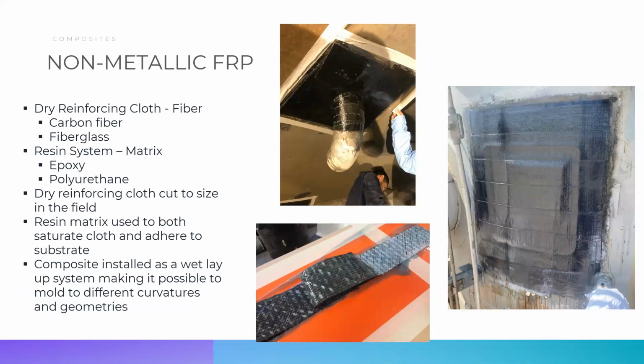The great part about this system, and if you're looking at this application here in the top left, is it's moldable. So it's a dry cut cloth. You can fit it to whatever geometry you need. So it's cut to size in the field, and the resin allows it to mold around any geometry. You can do patches, you can do wraps, you can go over tees, bends, different geometries. So it's always customizable. You don't have to fabricate anything offsite. It's ready to go out of the box.